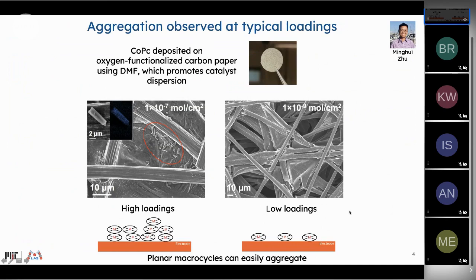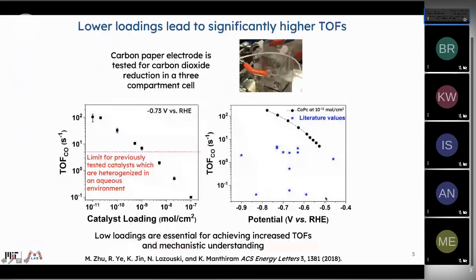So our physical picture now is that we have isolated sites, and this is relatively enabling for kinetic studies. So what we can do here first is see what the physical consequences of this lower loading of the catalyst are if we optimize for turnover frequency instead of current density, which is the usual way in which these catalysts are probed. Here on the y-axis, I have turnover frequency for CO, and on the x-axis, I have catalyst loading. And you'll see that as I go to lower and lower loadings, the turnover frequency, which is the number of CO2s converted to CO per active site per second, increases dramatically. Historically, the sorts of loadings that were used, which I showed a moment ago, around 10 to the minus 9 moles per centimeter squared, gave a turnover frequency of, say, 1 to 10. And this is then the historic limit for a heterogenized molecular catalyst doing CO2 reduction in an aqueous environment. But if we further reduce the catalyst loading, you can actually get a dramatic enhancement in the turnover frequency, up to about 100 turnovers that we observe here.